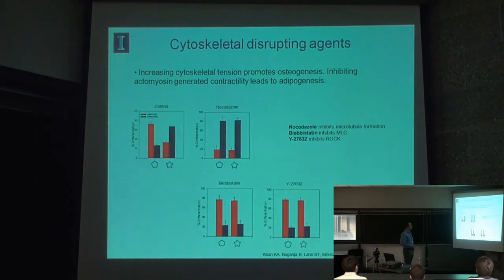So we thought this was pretty cool, so we went to try to figure out what was causing some of this and whether we could attribute this directly to cytoskeletal tension, so we used some pharmacological inhibition studies. Here's our control condition, where we get fat on the flowers and bone on the stars. When you treat these cultures with nocodazole, which inhibits microtubules and can lead to a high degree of cytoskeletal tension in the cells, but using a concentration where the cells remain viable and they stick to the shapes, we see that we get abrogation of this trend, where now all of the cells are turning into bone.